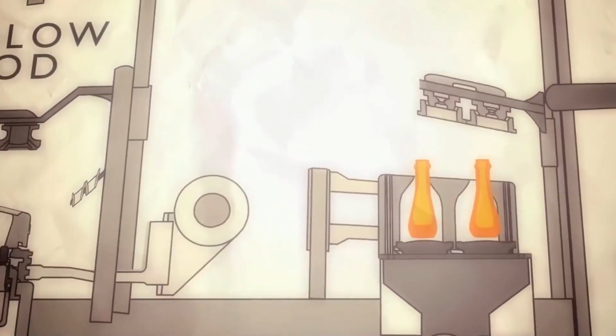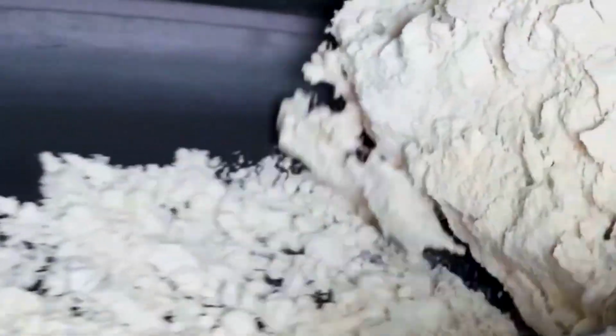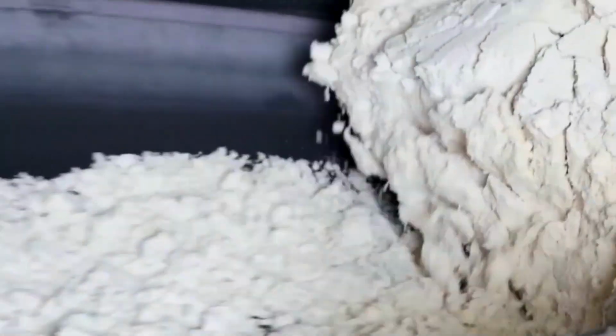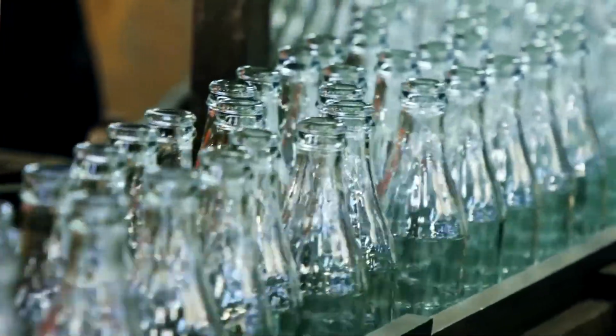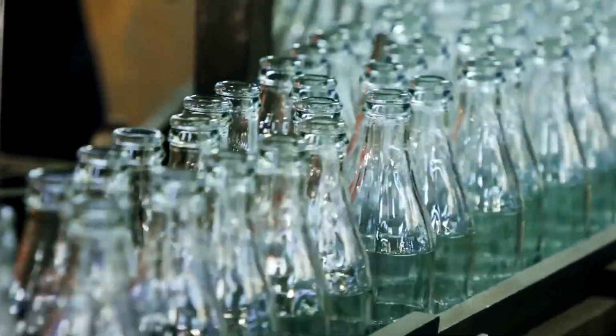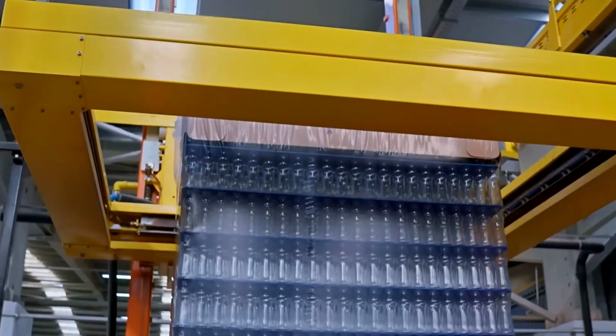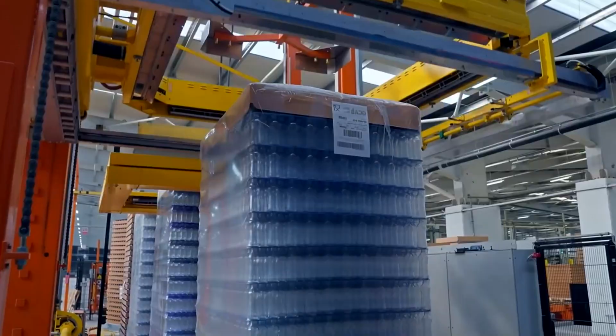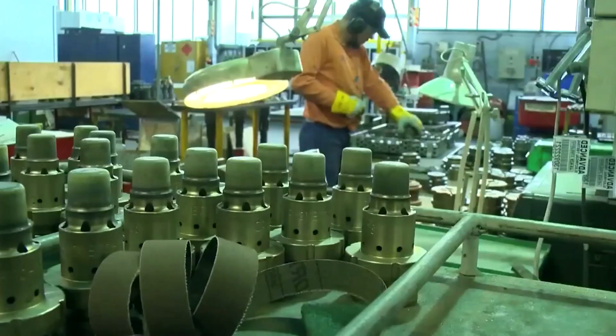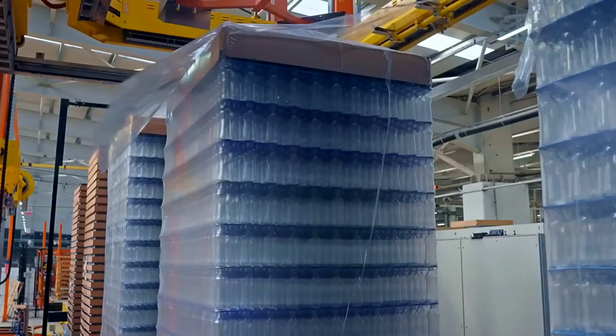bottles and food jars. The sequence begins as a drop of molten glass, a gob, is sheared from a continuous stream. This fiery teardrop, glowing at 1100 degrees Celsius, possesses the perfect viscosity for shaping as it falls into a preliminary mold, where a jet of compressed air strikes from above, forcing the gob outward to form a hollow, bubble-like shape known as a parison.